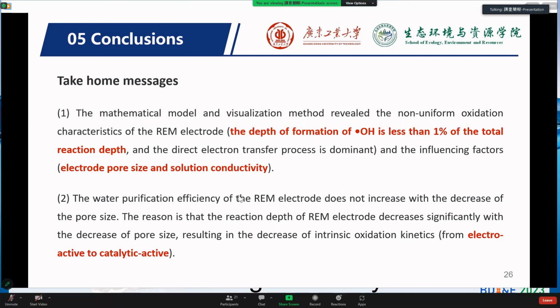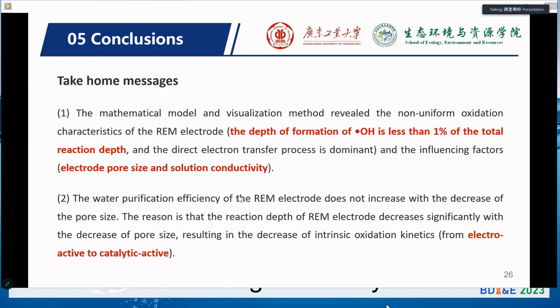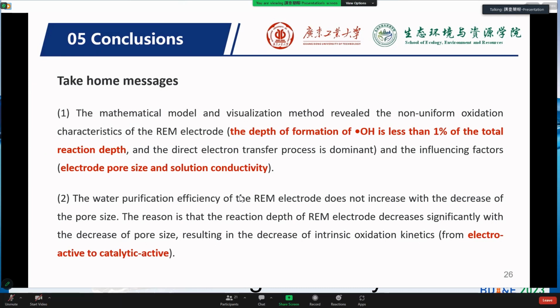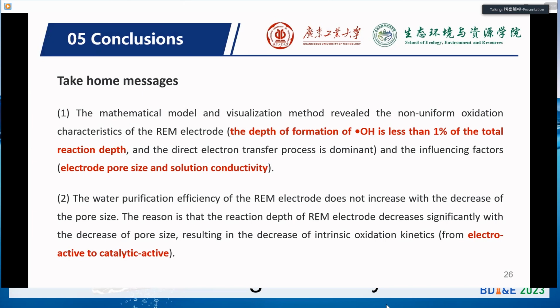So the second message is that we found that the water purification efficiency of the flow-through electrodes does not increase constantly with the decrease of pore size, although a smaller pore size significantly increases the mass transfer, and that is the main benefit of flow-through electrodes as compared to flow-by. So the reason is that the reaction depth of the REM electrode decreases significantly with the decrease of pore size, resulting in the decrease of the intrinsic oxidation kinetics. And it drives us to focus more on the catalytic activity area of flow-through electrodes instead of